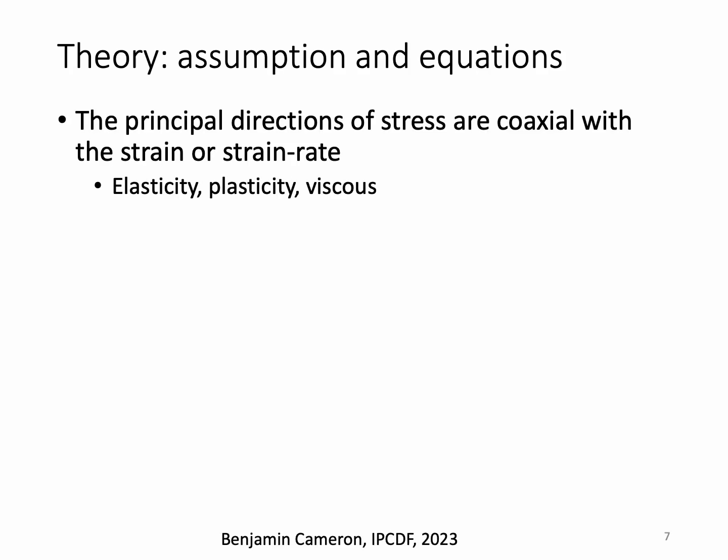So the main assumption is that the principal directions of the stress are aligned with the principal directions of the strain in the case of elastic deformation. If we had plastic deformation with negligible elastic strain, we could also say that the principal directions of the stress are aligned with the strain rate.